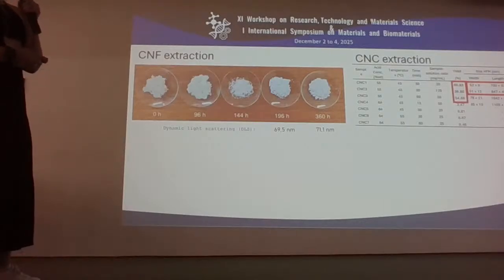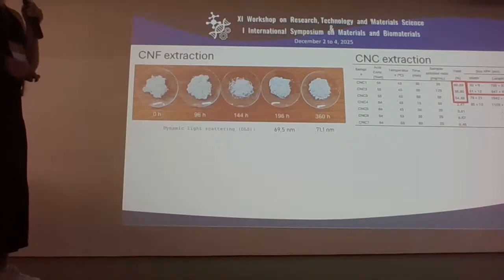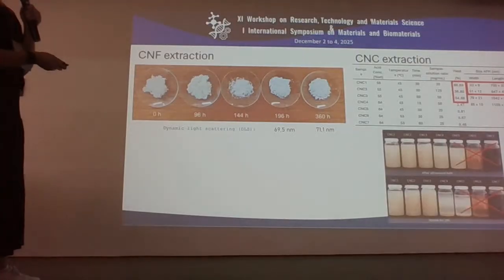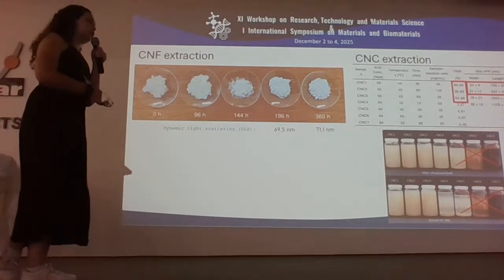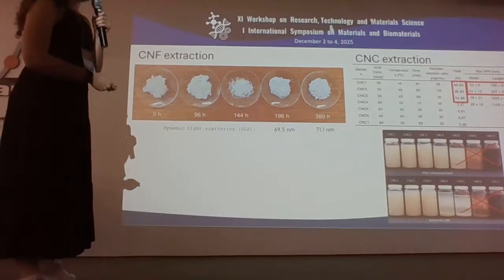And for the CNC extraction, we varied the main conditions like temperature, time, and acid concentration. With lower temperatures and lower acid concentration, we have high yield and also smaller size length. So this is a good result. And when we use a higher acid concentration and temperature, we have a lot of degradation.